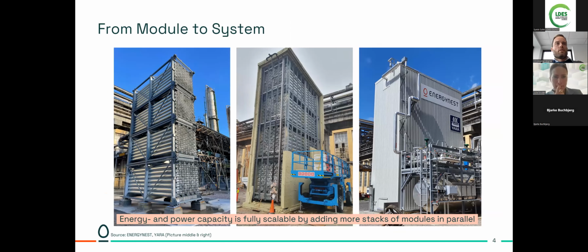And the way we construct a storage is also very simple. We have a concrete foundation with load-bearing elements, as you see on the left side. This picture is taken from our project with Yara in Norway, which is currently in operation. On the left side picture, you see a stack of 4. They are hydraulically connected in the vertical direction. When you charge the battery, we have hot fluid entering at the top, and then cold fluid coming out at the bottom. Then when we discharge, we reverse the flow. And as I said before, we can use water, steam, thermal oils, or also other fluids.